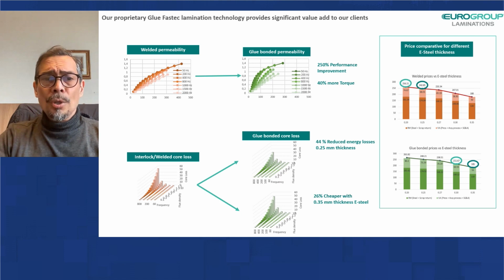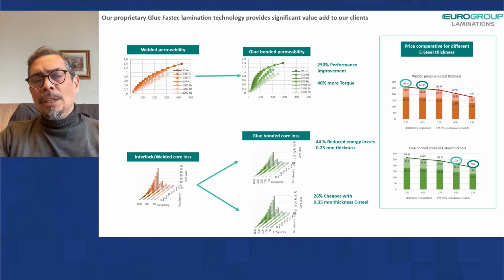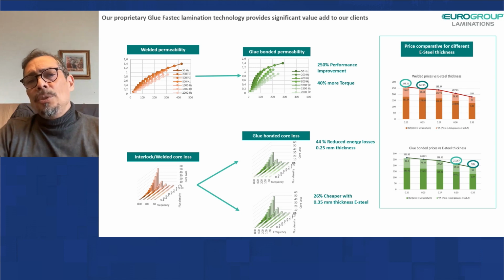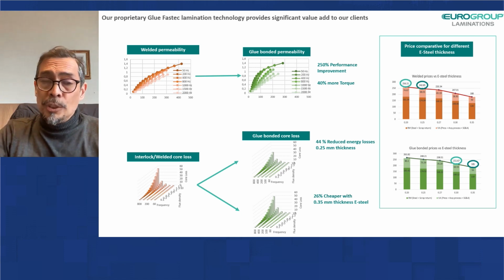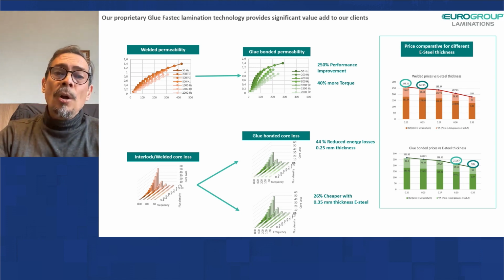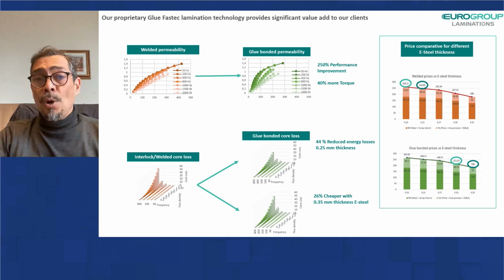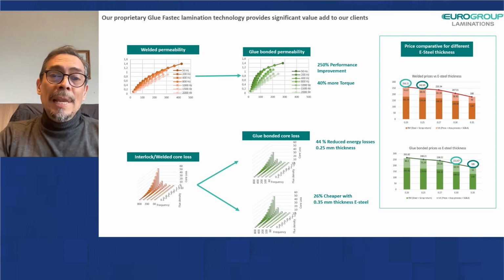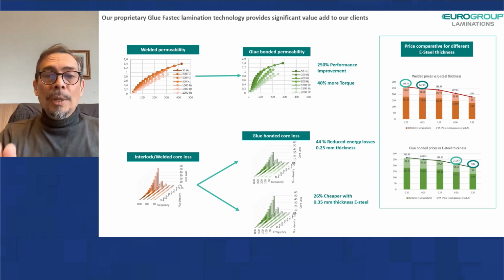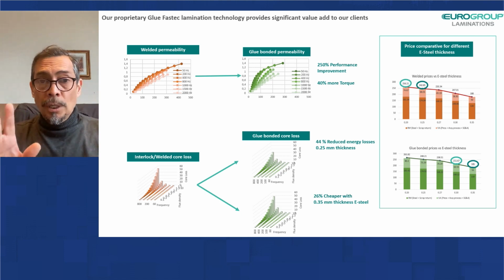This is a study that shows on top the BH curve. BH curve is the magnetization curve. So you have, for a given amount of current, a magnetic density that is called magnetization. It is measured in Tesla. On the left side in red, you see the magnetization curve is very soft, is very slow. The slope is small. In green, you have a much bigger slope, and you can see that with less current, you produce a higher magnetization, meaning that with less current, you produce more torque in your car.